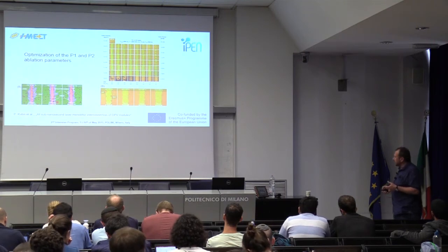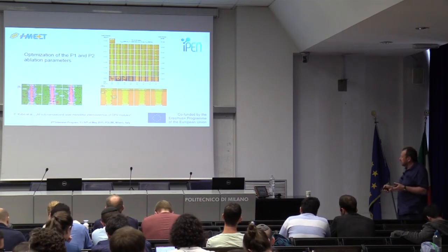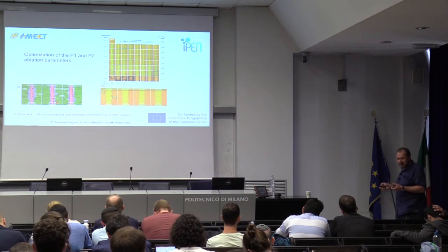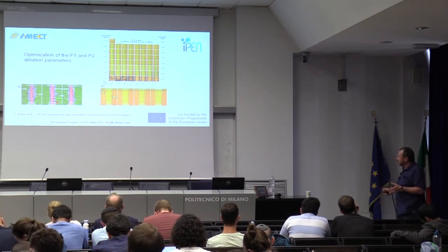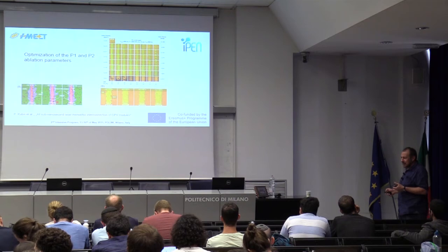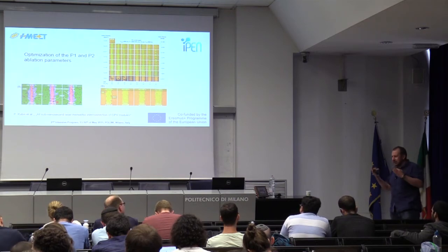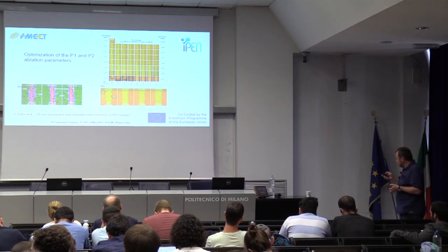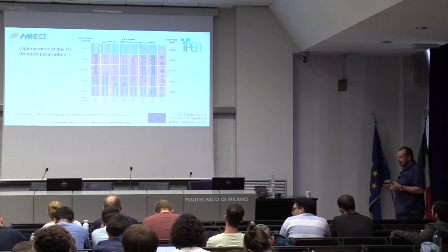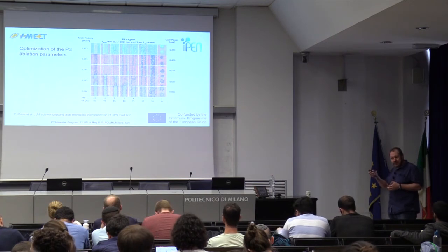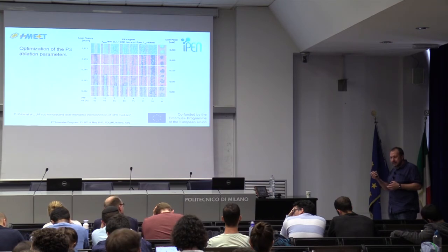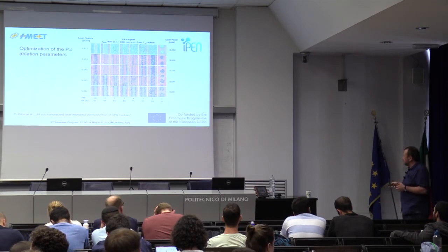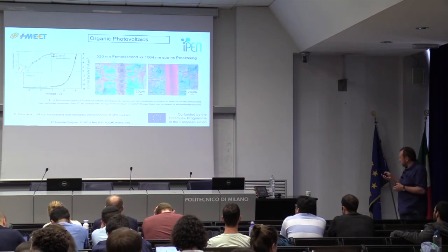But what was interesting in this work is that if you do it properly, so to say, then you damage this IMI in this region in a way that you have some higher regions at the edges, and they actually help to contact, well, when you're doing the P3 grooving, then you have to contact it to the bottom. And these higher edges of the IMI are actually helping to improve the contact. And here is the result.